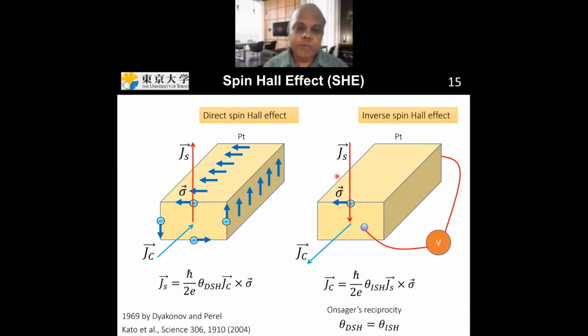These two effects are actually the most important effects in spintronics because the spin Hall effect gives the opportunity to create spin current without any magnetic materials, and the inverse spin Hall effect gives the opportunity to detect spin current. So the way to detect is you inject spin current into platinum, and it will produce a charge current. Now, if you put a voltmeter, then you can detect your spin current.